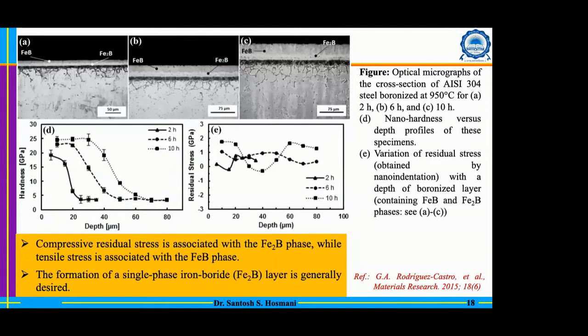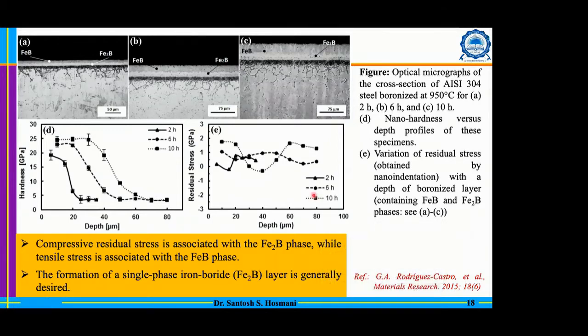Now, as I mentioned previously, why we don't want to have two layers together. So here is one example. Here they have studied the AISI 304 steel, and you can see clearly in the microstructure that there is a formation of Fe2B as well as FeB. And you look at the nano indentation study, where they mention the hardness profile as well as the residual stress profile. And here you can see figure E, that residual stress profile, I will just use a laser pointer. Yeah. So in the residual stress profile, you can see that.